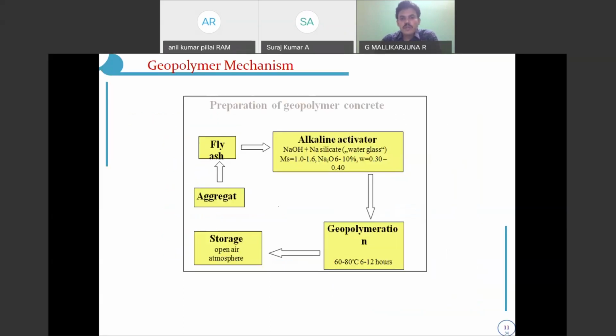For this geopolymer mechanism, we consider fly ash and alkaline activators of sodium hydroxide and sodium silicate. After that, you maintain a certain temperature of 60 to 80 degrees centigrade for 12 hours. Whatever specimens you have cast, the cubes or the cylinders, you have to store them in the open air atmosphere, and you get a certain amount of strength.